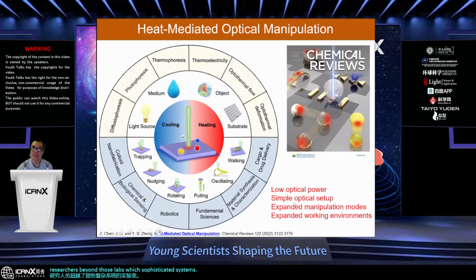Further, this type of manipulation has expanded manipulation modes. As mentioned, not only translational, but rotational, and even more, as I will mention later. There is also an expanded working environment. Here, working environment means that we can achieve the manipulation not only in solution or in vacuum or air, as traditional optical tweezers have achieved. We also show that we can move this from liquid into the solid phase, and we can achieve this on a solid substrate or even in a solid bulk environment.